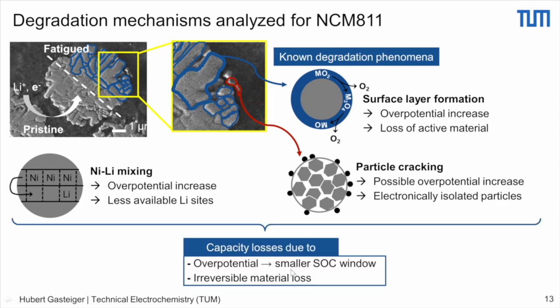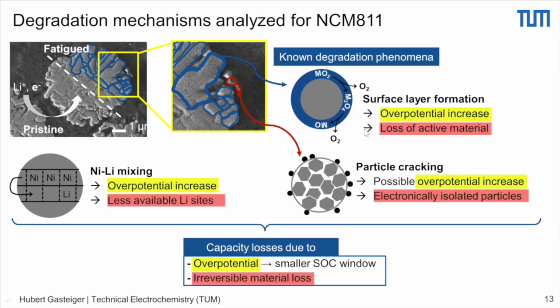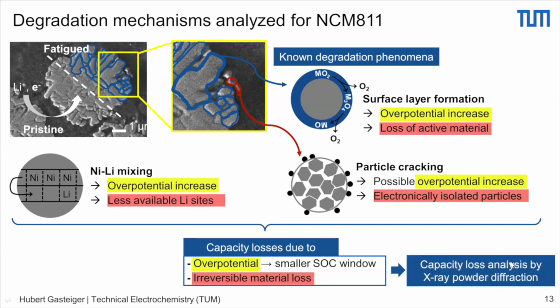So two effects also. What we find is that all these three contributions may play a role. And we have in principle two effects: an increase of overpotential, which can be caused by all of those, which would lead to a smaller SOC window and thus to a loss of capacity. And we can also have irreversible loss of material, either by converting the surface into an inactive material, by electronically isolating materials in the center of the secondary agglomerates, or by having less lithium sites available due to blockage by transition metal. And so this capacity loss we want to examine by X-ray powder diffraction.